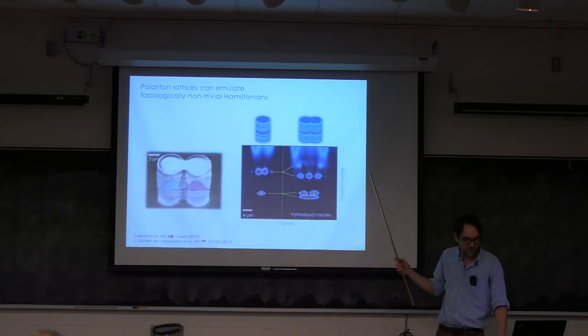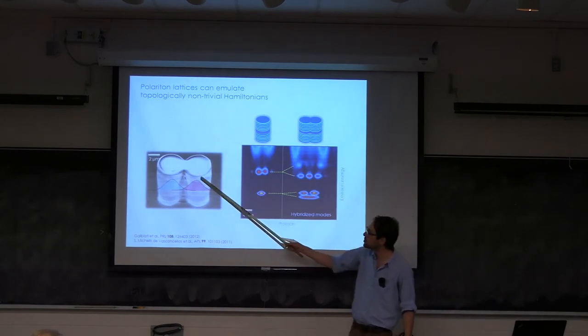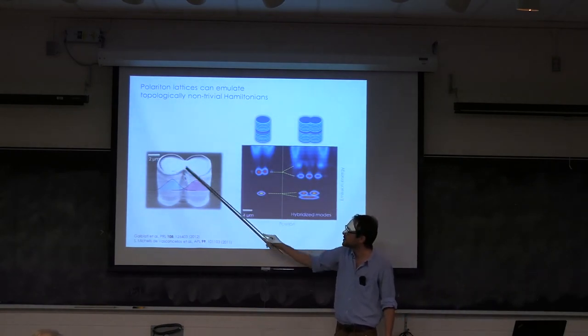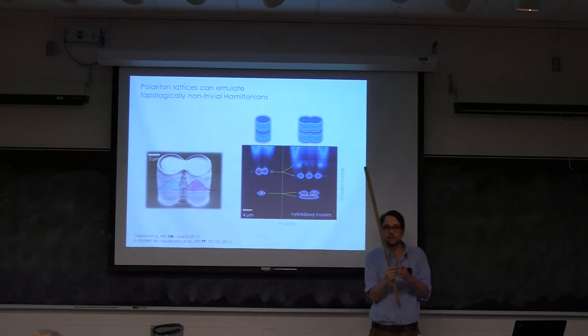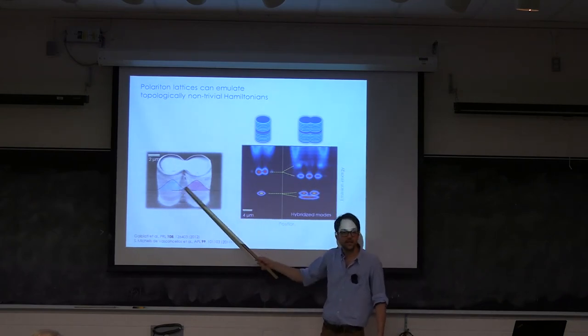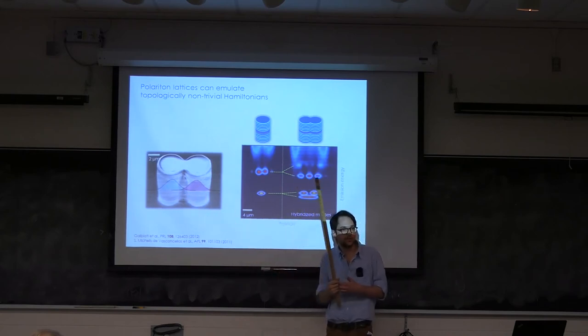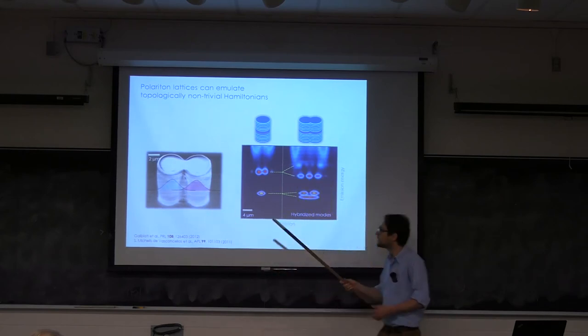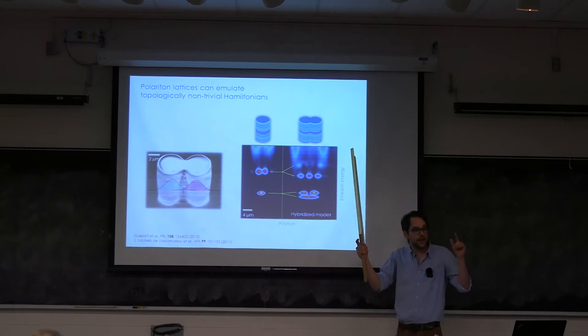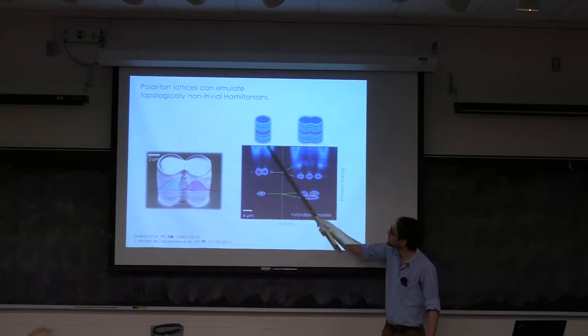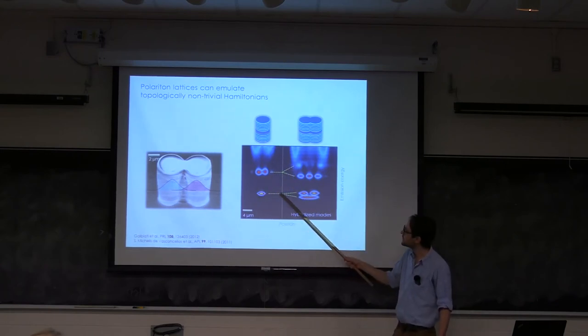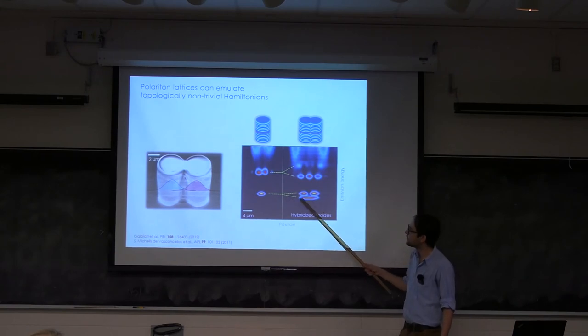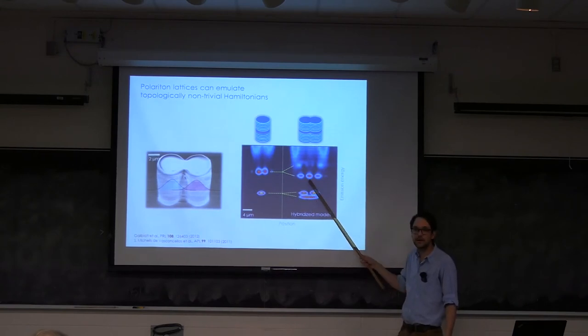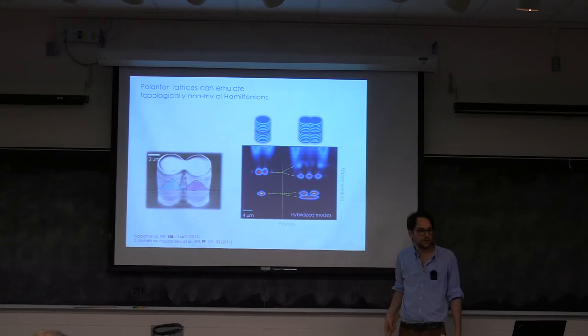And what you can do eventually is to make more complex structures by coupling two of these together, by etching them with a center-to-center distance that is smaller than their diameter. As a result, the eigenfunctions of each of these pillars overlap, and they are going to hybridize and form molecular-like states. So this is a single pillar with a ground state, and here the ground state is doubled: you have a bonding mode and an anti-bonding mode, and it is the same for every orbital.